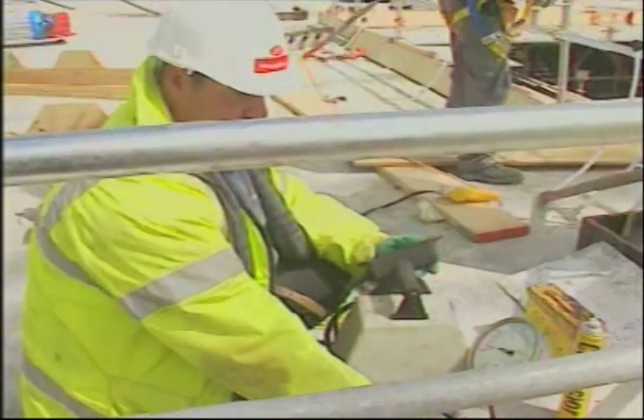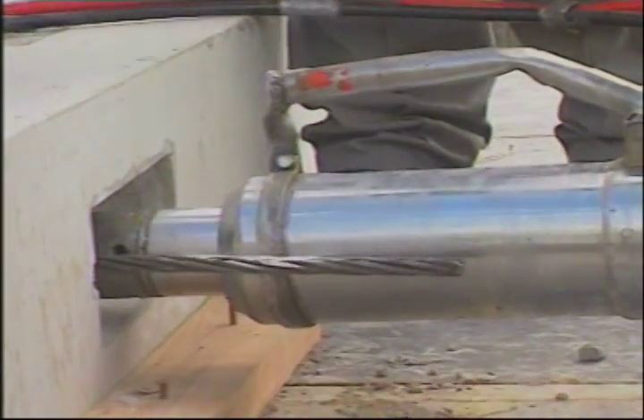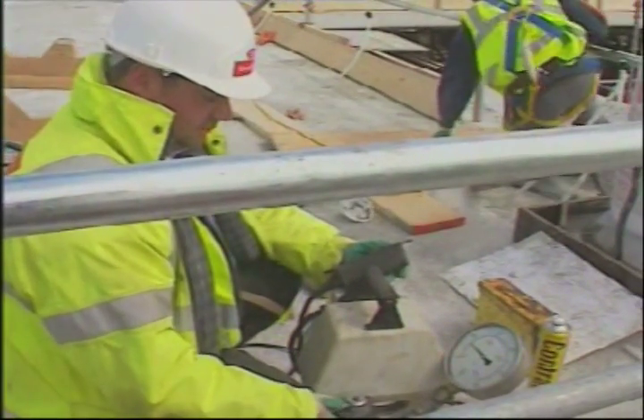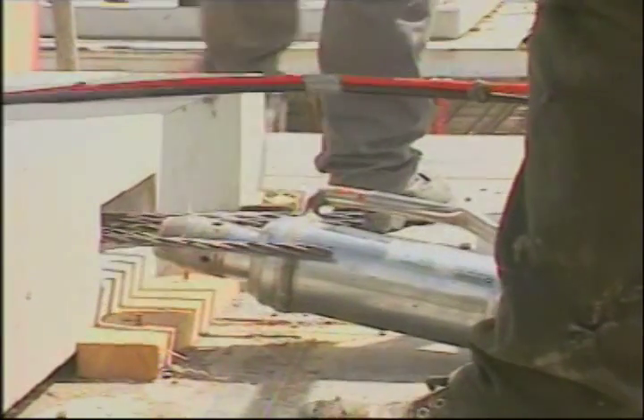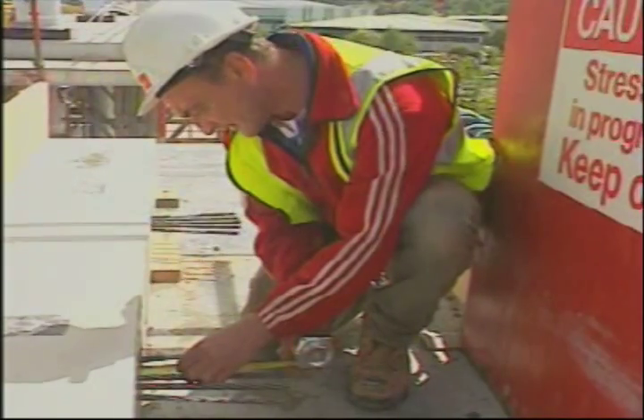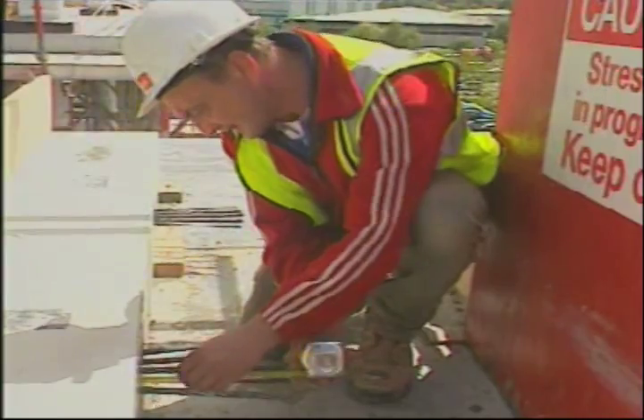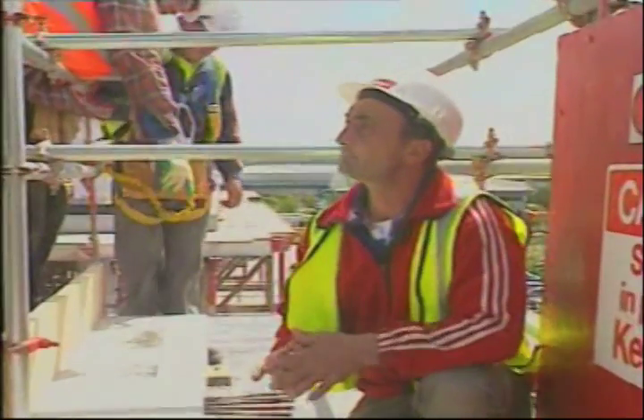At a time typically 48 to 72 hours later, the concrete has reached compressive strength and is ready for final stressing. The jack, hoses and ancillary equipment will again have been checked thoroughly. They've now been stressed to the required design loading. 107, 110. The elongation of each is measured and approval obtained to cut and seal.